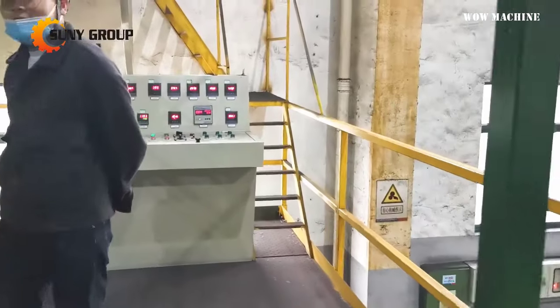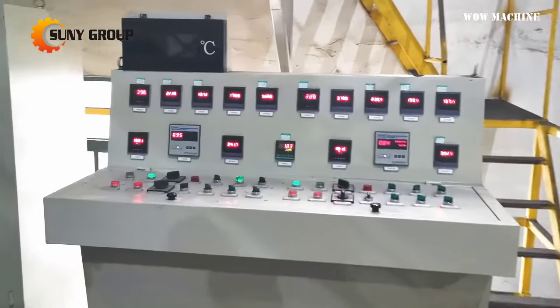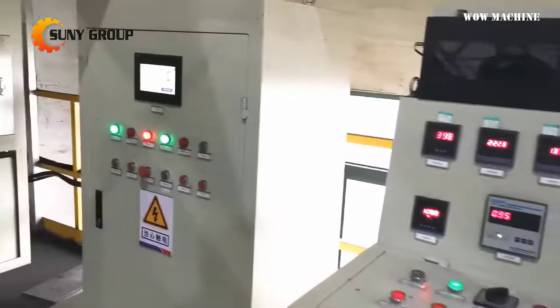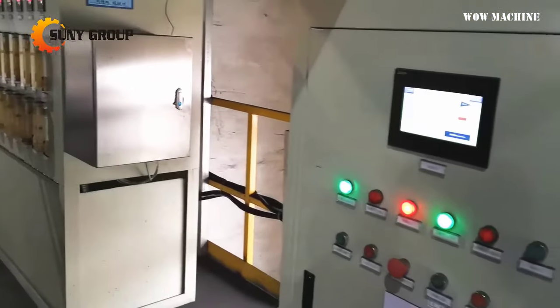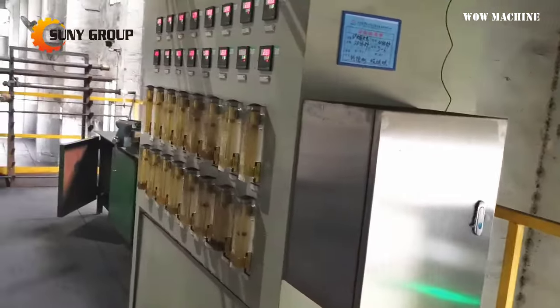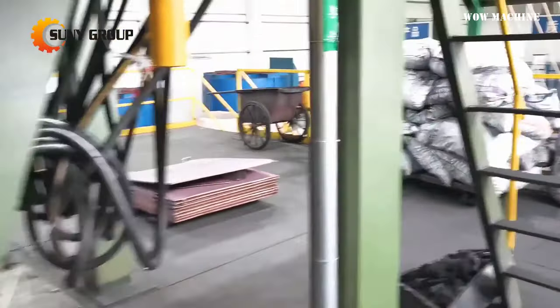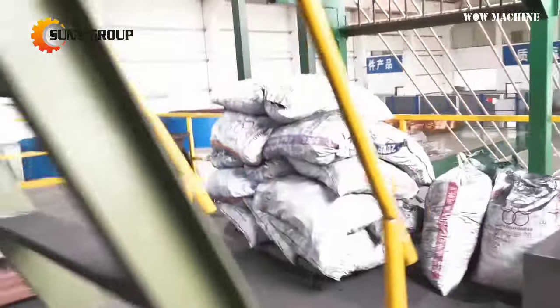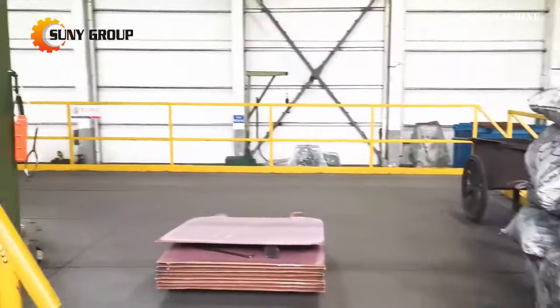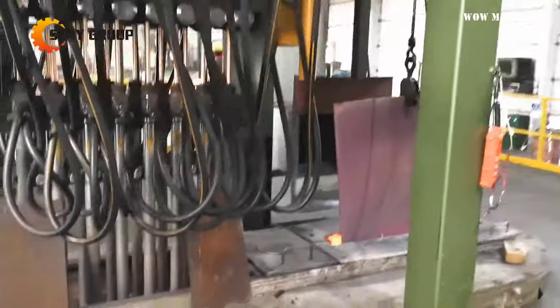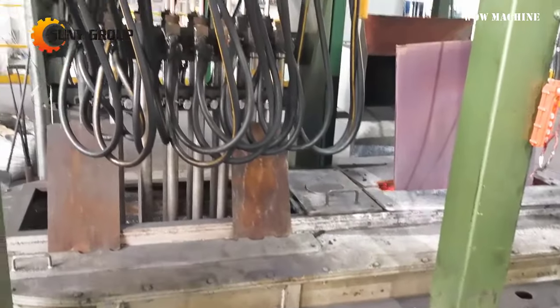Rolling. The solidified copper billet is then transferred to the rolling mill. The rolling mill reduces the billet's diameter and increases its length, gradually transforming it into a copper rod. The rolling process not only shapes the copper but also enhances its mechanical properties, such as tensile strength and ductility.